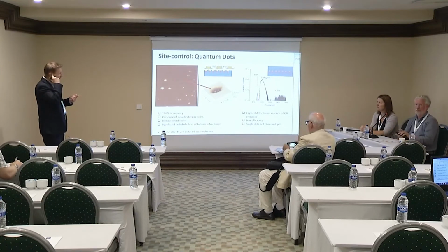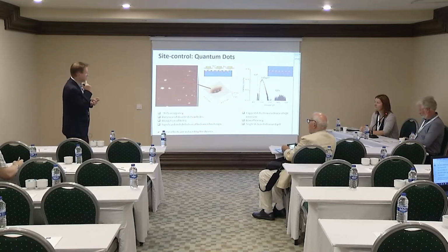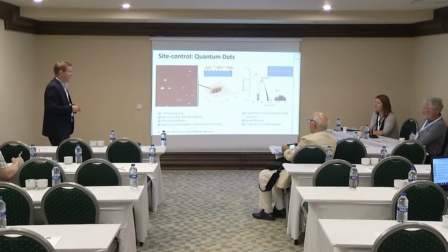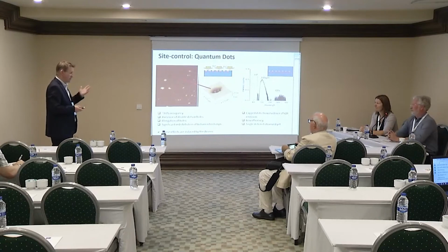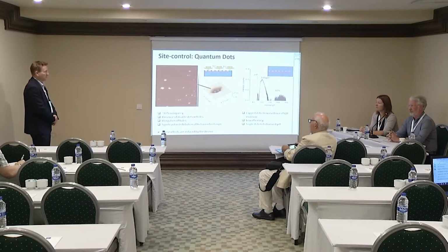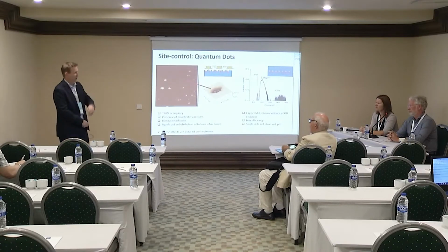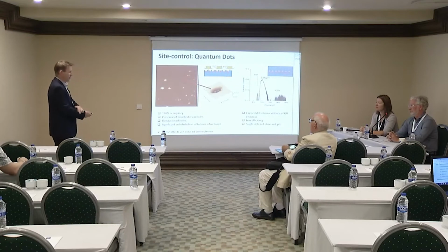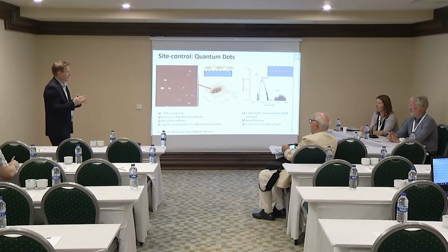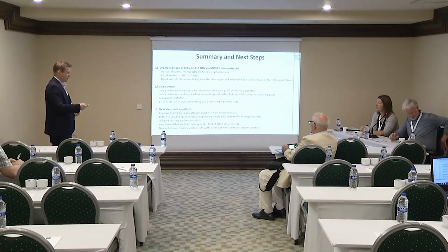I think it maintains the shape fairly well actually, but it's to clean up the surface, particularly for the MOVPE to put it in the reactor. So at the moment it's dry etch. We are exploring other things like the LAO that Ian mentioned, and possibly even nano imprint type technologies that we could use with either etch process. With dry etch we get quite steep walls with a little bit of a pit at the end. If we do wet etching, we get much more rounded holes. So I think we've got a number of options for exploring the interaction of the droplet etching with that.